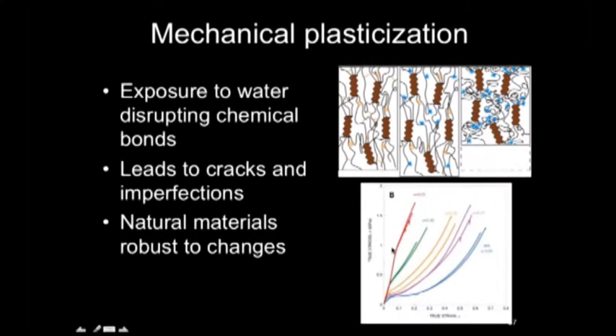In this graph here, it's quite a colorful image, but if we look at going from purple all the way to red, these fibers are at a state where they were wetted originally and to various degrees. That's what these degrees mean. The higher degree is basically the more dry the fiber is, and therefore it's a little bit stiffer. But as it's wetted, it becomes stretchier. It does lose a little bit of strength, but this isn't catastrophic to the fiber itself and is still functional in many applications. So we wanted to know, does this make a difference in spider silks and in other types